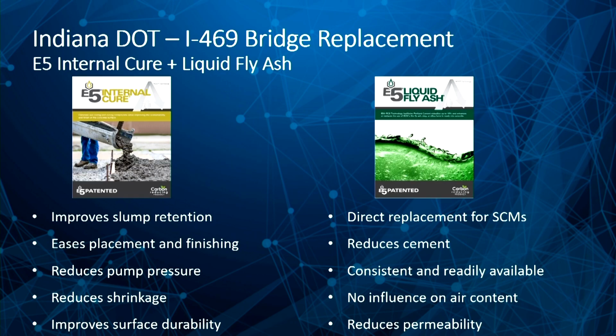Individually, for fresh properties, with the internal cure, because that water of convenience is not evaporating, it's being contained within the concrete, slump retention is not an issue. Folks don't have to add water when the truck arrives, halfway through the discharge. They don't have to add it to the surface. These products were created by a third-generation finisher for finishers. They're meant to make placement and finishing easier and make concrete more durable so the finishers don't get callbacks later because the concrete has not performed well. So it eases placement and finishing, right?